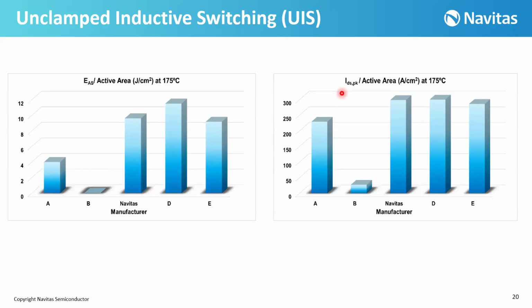Also, here is the IDS peak, or the peak of the current, and again we normalize it based on their active area. Both of them are at 175 degrees C, so they are at high temperatures. And again, we have a better UIS capability regarding the high current compared to the trench devices.